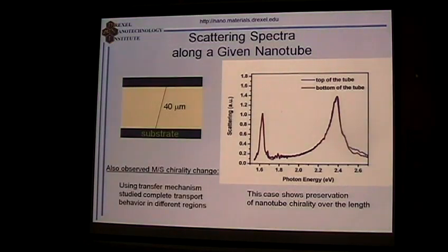However, it was also shown that there may be some changes. Moreover, it was recently shown that, for example, by irradiating a tube it's possible to introduce defects, introduce changes. For example, changing metallic to semiconducting behavior of carbon nanotubes by modifying, by oxidizing tubes. So it gives opportunity to again study changes in the electronic structure and properties of carbon nanotubes.